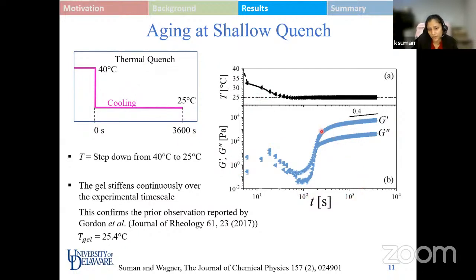We can see that within a few seconds, thermal equilibrium is achieved using the Peltier plate system. Initially, the value of modulus is low, because of the liquid-like state, and it undergoes an intersection at a specific time, and then undergoes a gradual slow increase in the modulus value with an exponent of 0.4.